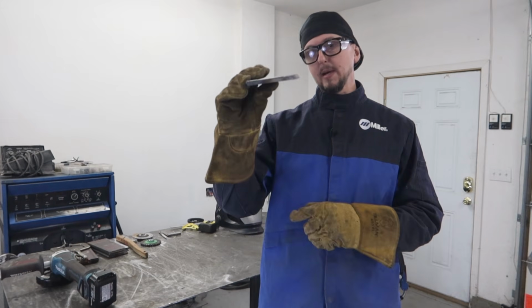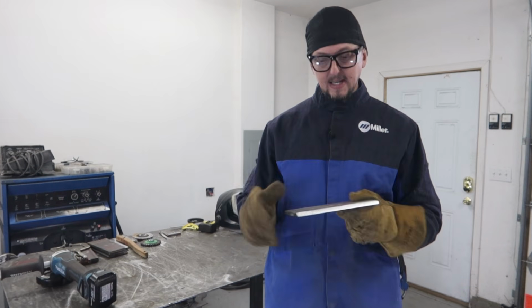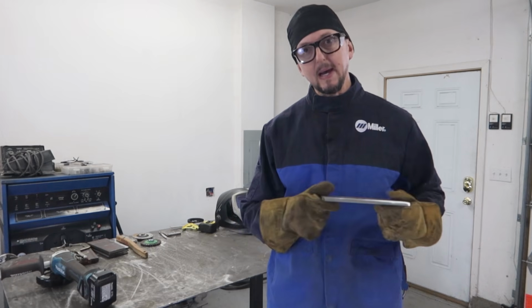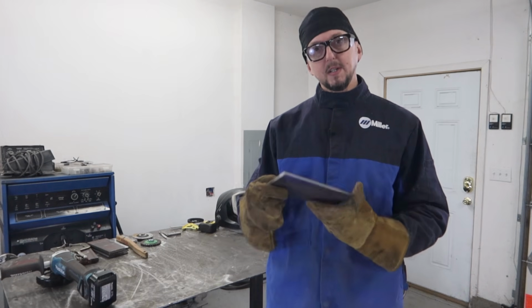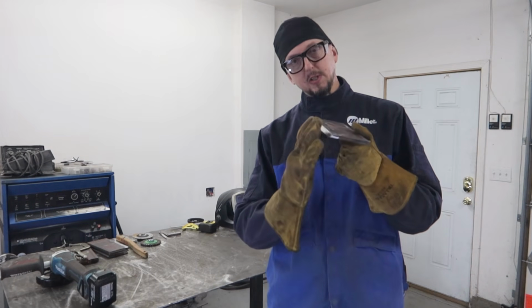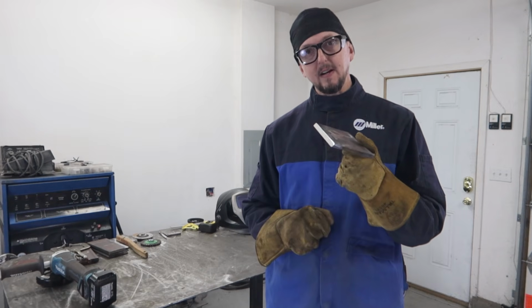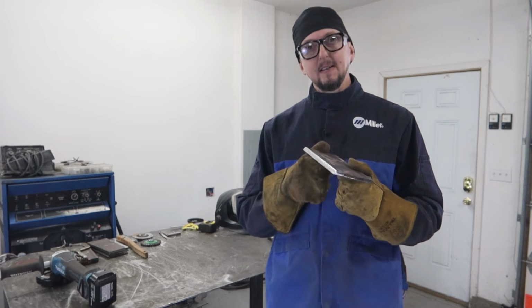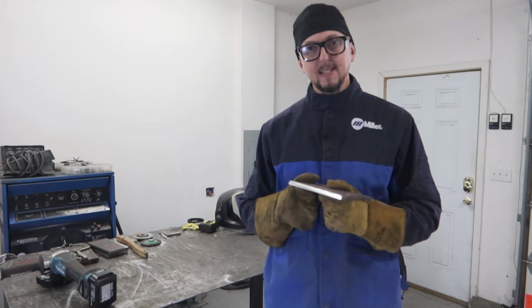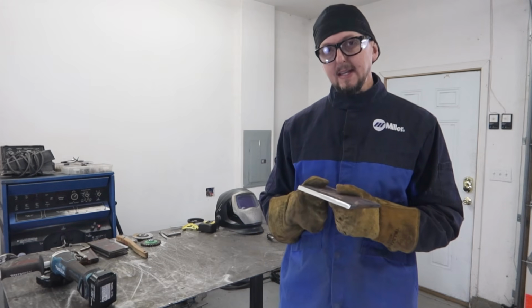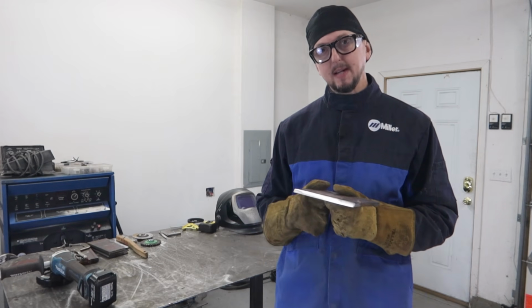So once it's all prepped and you have a knife edge, then you just take that to a pedestal grinder and run it back and forth a few times, or you can take a grinder at an angle and just put a very slight little flat on there, about a 32nd of an inch or so, no more than a 1/16. So I'm going to show you how I do that next, and then we'll go into the fit up process.